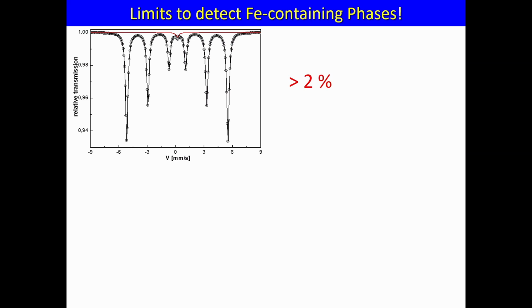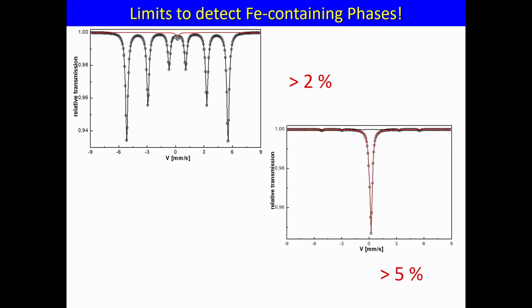So, limit to detect iron. Because sometimes, as you were mentioning, I have a nice sample. Is it possible to detect some impurity? Here, it corresponds only to a theoretical spectrum. Here, I put a single line over a sextet. If I put 2%, you can see the effect. If you add statistics, it will be difficult. The same if someone is writing in a paper, I found this impurity at 0.5%. Okay. The opposite is you have a magnetic impurity on a single line. And look, you need 5% to see something. With statistics, that means you need 10%.